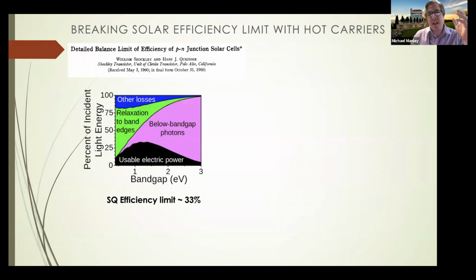To understand that, you have to go back a bit to probably the most famous paper in solar energy, which is this Shockley-Queisser paper from 1960, where they took the spectrum of the sun, and then they started to consider, okay, what efficiency can we get? And they have a plot here, and this is the band gap. Essentially, if you make your band gap too wide, then you're letting photons of energy below the band gap pass through, and so you start to lose on that.